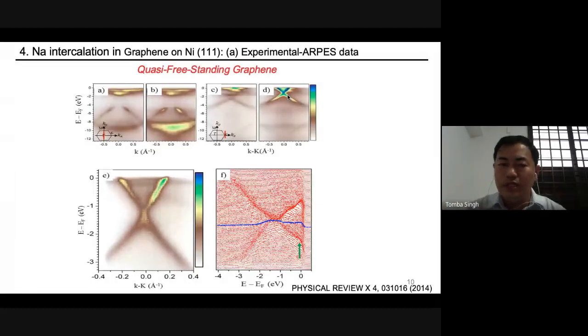If we look closely at figure E, we observe that the upper cone and the lower cone are touching at a point, almost no band gap is here, only the linearity is a little modified. That means we can recover the pristine property of the graphene just by intercalating one layer of sodium. So the graphene is behaving like quasi-free-standing, just floating, even though it is sitting above a substrate. This is the target of this work.